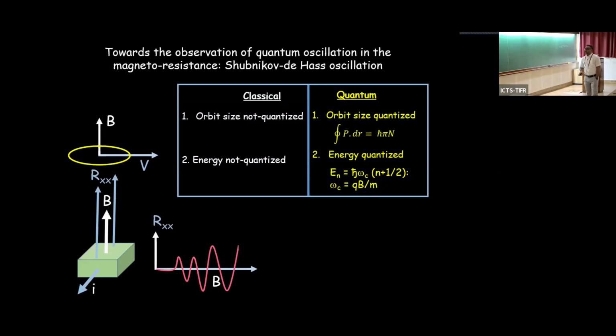Okay. So what you see, if you send the current, you apply the magnetic field and look into the longitudinal resistance, you see an oscillation in the magnetic field, because by changing the magnetic field, you are changing the distance between the Landau levels, and when one crosses the Fermi level, it gives rise to the oscillation in the resistance in the longitudinal direction. This is known as quantum oscillation in the system.